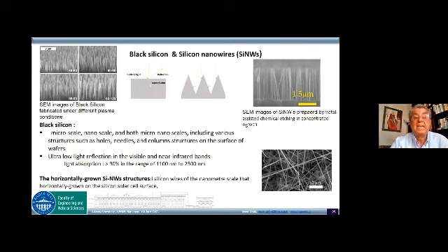Black silicon, silicon nanowires. These are very important because you know the properties of silicon and its refractive index create some problems. By producing silicon nanowires or creating black silicon by etching, you can play with the absorption and reflection at the nanoscale. And the new part is the horizontally grown silicon nanowire structures. Lateral growth of nanowires on the silicon surface will help significantly in improving absorption and reducing reflection.